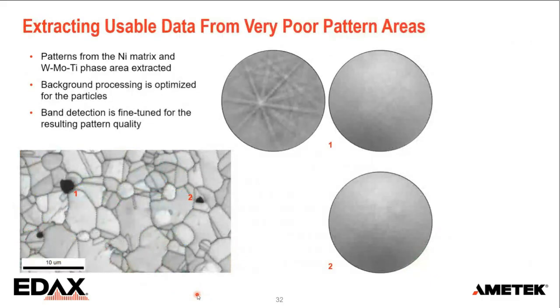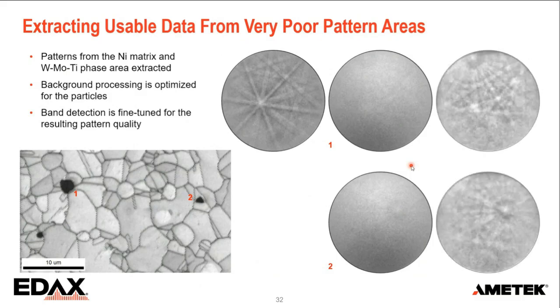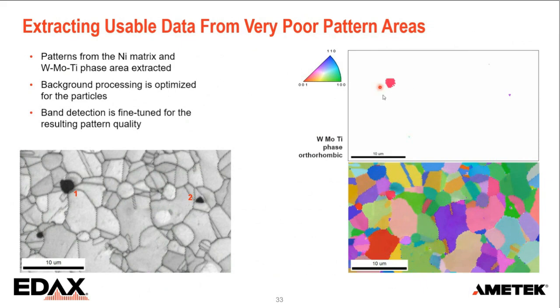That's one thing. Another thing, and this one is even more pronounced. When I look at this map, it's a nickel alloy with some tungsten, molybdenum, titanium intermetallics. Initially, these just looked like pores or dirt, perhaps, because there was just no signal coming out of them. But when we take those points and get a pattern, if you look from a distance, you may be able to see a few bands, but you might think that's wishful thinking. But if I really optimize those patterns, we can still get this out. And now you can clearly identify the bands, the different zone axes, and that is very indexable. So again, I re-index those points and I add them into the data set.